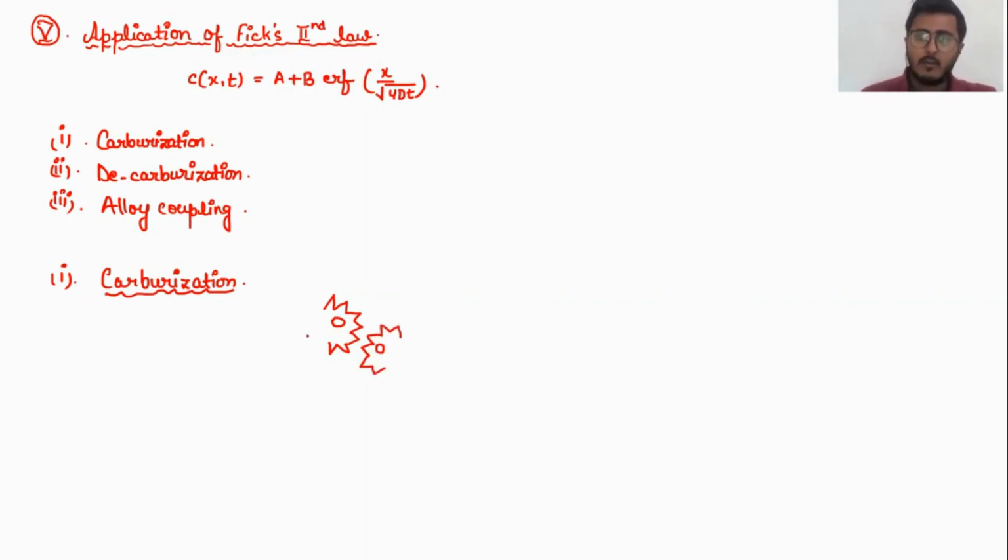The gears undergo different revolutions inside each other, and because of that, there are chances of wear and tear because of friction. So it is very important that the hardness of the surface is quite large. Carburization is a surface hardening technique where we diffuse carbon over the surface. The carbon diffusion pins down dislocation movement, giving strength or hardness to the surface.